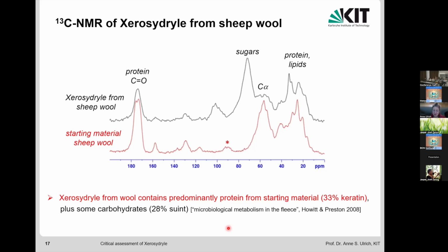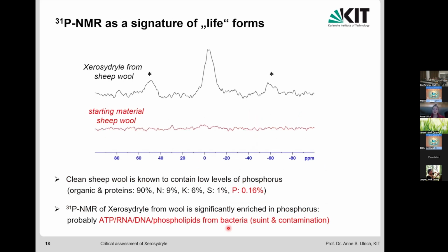And we decided to look at the phosphorus spectrum, because phosphorus in DNA and RNA and ATP, our energy molecules, and just the phosphates floating around in the cell, is very characteristic of life. And what you see here is a phosphorus NMR spectrum, solid state NMR, of the dried sheep wool sample and of the starting material, pure sheep wool. And you see, indeed, the Xerosydryle has accumulated lots of phosphate, lots of phosphorus, even though sheep wool keratin has hardly any phosphorus. So the Xerosydryle sample must be contaminated with stuff from bacteria, the suint, and maybe extra bacteria that flew in during the long time of sample preparation.